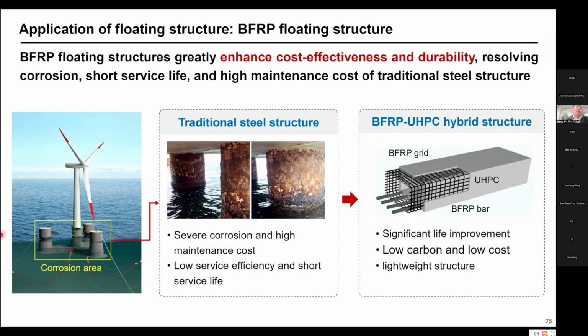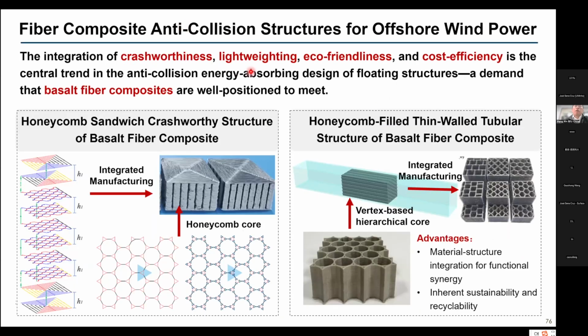And also for the floating area, sometimes the crash control. So these are also very important issues. We need lightweight, economical, friendly materials to control the cracking, to resist the cracking. So we recently developed a kind of integrated manufacturing way with this kind of honeycomb structure by 3D printing. Currently, we're still in the experimental stage. So the resin with the chopped basalt fibers, and the latest one we use the continuous fibers to print this kind of honeycomb structure to resist the crushing.